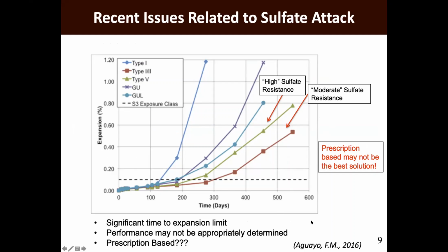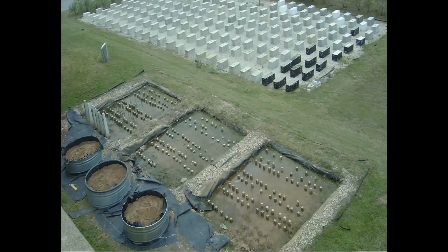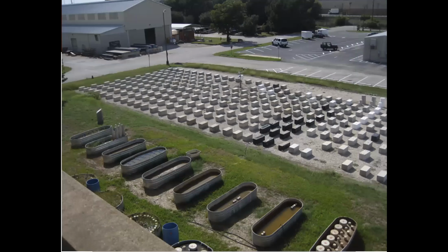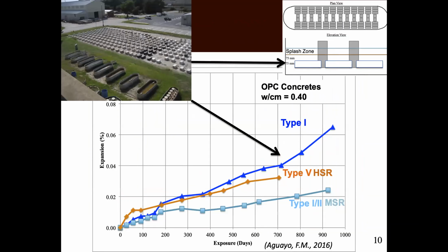So we thought that maybe this is not particularly an issue, or maybe this is an anomaly for the results. And so we actually have an outdoor exposure site where we did testing in real conditions, heat, temperature, humidity, and moisture as part of the equation. And from this sulfate testing site, we've collected data over 3 or 4 years now, and we're starting to see similar results where the type 5, which is a high sulfate resistance, is performing worse than a type 1, 2. So again, sometimes just the production of the cement alone, while it indicates a particular chemistry, may not have, for whatever reason, the actual performance that is required for a sulfate environment, right?